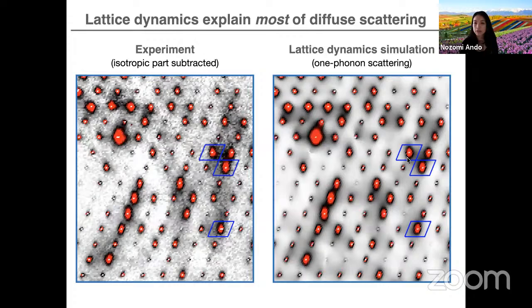And there are two things to notice here. The anisotropic shape of the halos is also explained by the lattice dynamics simulation. But here, the proteins are completely rigid, yet we're seeing a cloudy pattern in the background. So this was telling us that these halos actually scatter pretty far from the Bragg peaks in order to create a cloudy looking pattern.